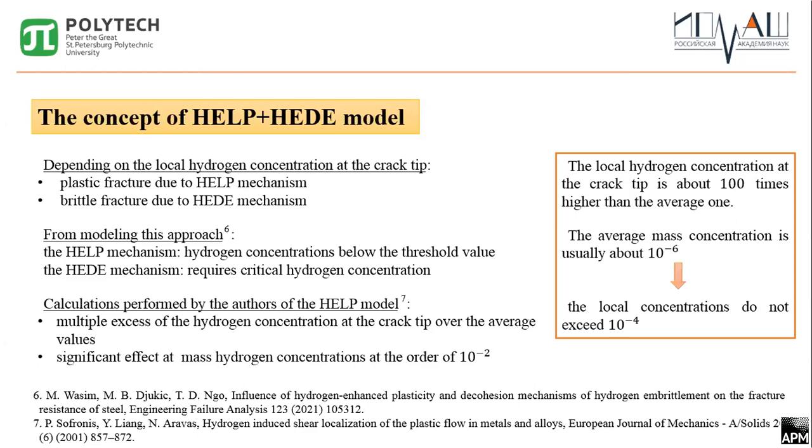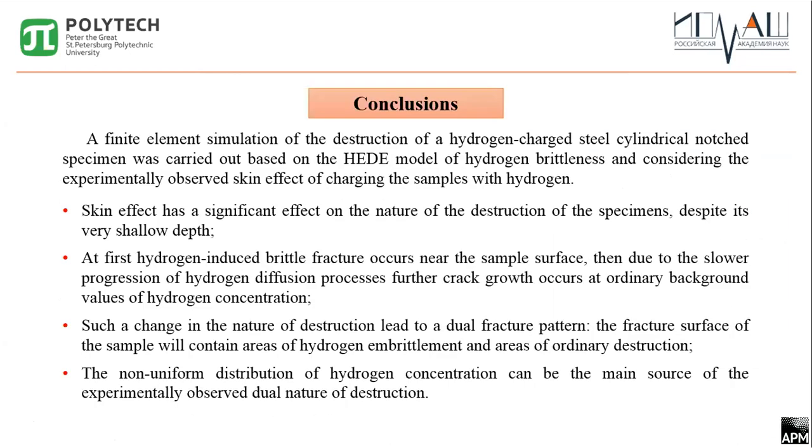Almost all publications on the HELP and HEDE models use the assumption of an initially uniform hydrogen concentration. The presence of such inconsistency in the known approaches allows us to say that the non-uniform distribution as a result of charging the samples with hydrogen is the true reason for the dual nature of the fracture observed in nature. And let's get down to the conclusion.